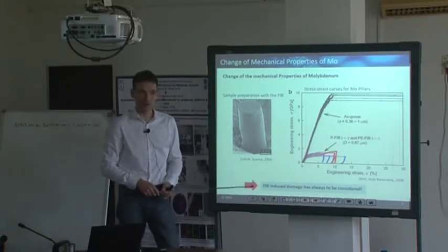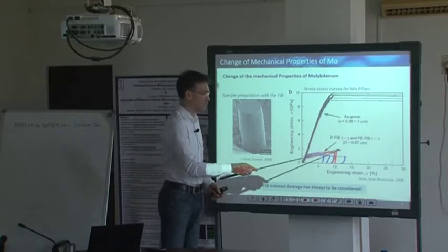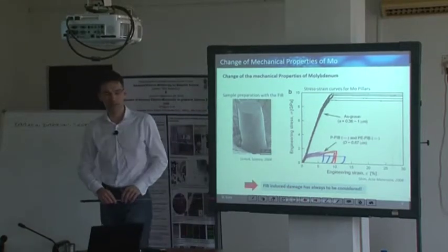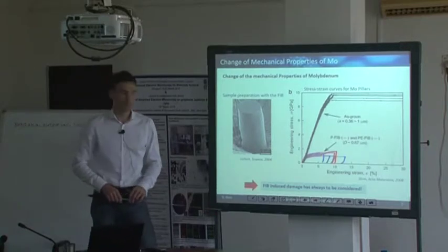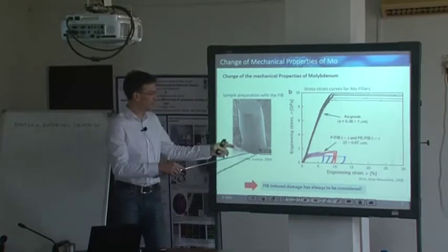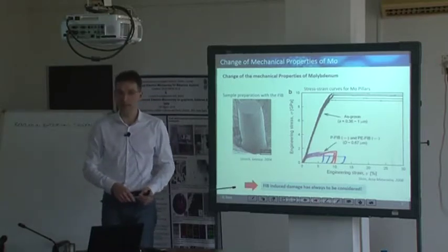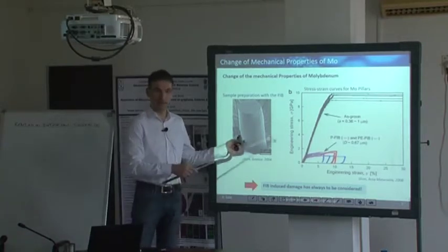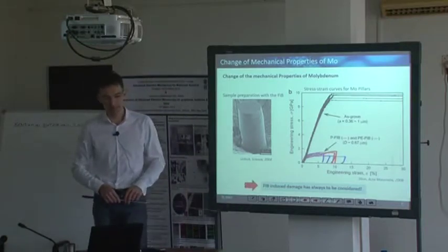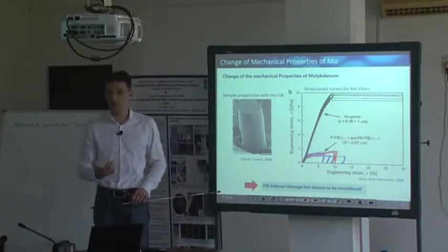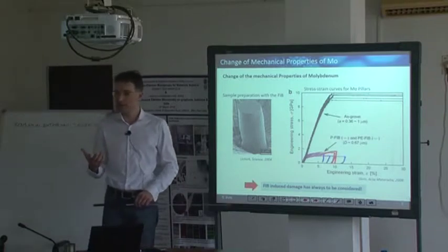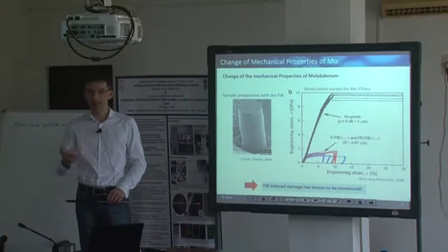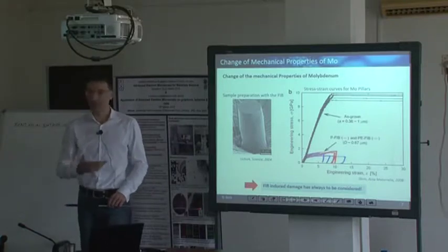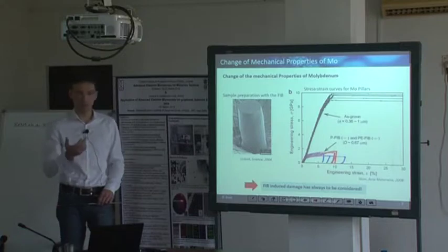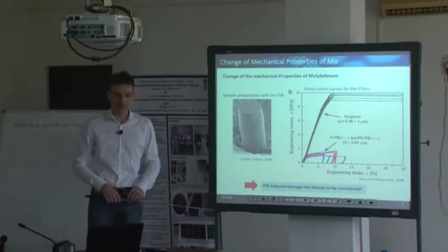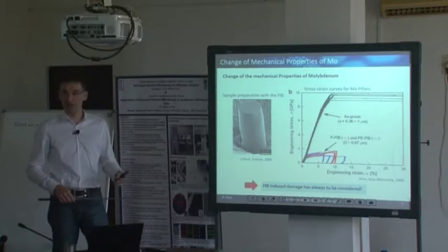So there is a clear difference just due to the fact that those samples here were prepared using a focused ion beam. And you have to be aware of the fact that in this particular case, you form this shell layer around it that might enhance the strength of the material, or that might lead to a reduction. On the other hand, if you conduct experiments in a gas environment, you have to be aware of the fact that your electron beam already ionizes your gas or your liquid. So the pH in the liquid might change simply due to your electron beam irradiation. So I mean, you have your electron beam that might change your environment.